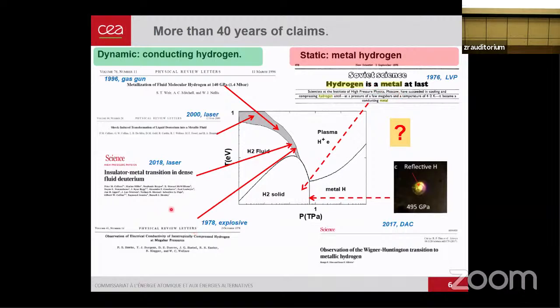In a dynamic approach, since you launch a shock or a dynamic compression, you heat at the same time. So the way you heat, the sample changes the temperature. And if you heat very slowly, you can have isentropic compression, so you don't heat too much. In all these dynamic experiments, they observed a change of conductivity, either by reflectivity or by measuring conductivity.